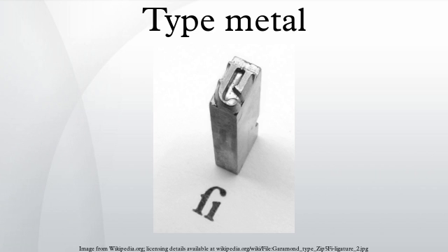Raising the content of antimony cannot be done without adding some tin too, because the fluidity of the mixture will dramatically diminish when the temperature goes down somewhere in the channels of the machine. Nozzles can be blocked by antimony crystals. Metals used on typecasting machines: eutectic alloys are used on Linotype machines and Ludlow casters to prevent blockage of the mold and to ensure continuous trouble-free casting. Alloys used on Monotype machines tend to contain higher contents of tin, to obtain a tougher character.